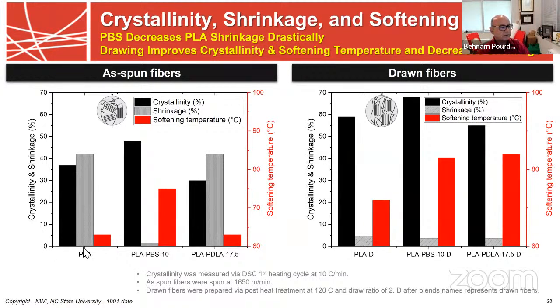And if you look at the PLA by itself, if you look at the black is crystallinity, you're less than 40% crystallinity, but you have more than 40% shrinkage. And the softening temperature is roughly about 63, 64 degrees. So these are the challenges that you have with PLA, which is partially oriented.